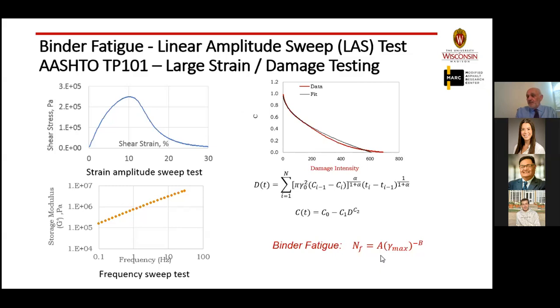So the number of cycles to failure in the binder is equal to A times strain to a power law function, or a power law constant, if you will. These A and B are related to the maximum strain. So if you look at the conventional fatigue equation, it definitely tells you it's all about the strain. If we all know this equation, and we use it in so many different applications, how come when we come to testing the binder, we only test at small strain and say, oh, well, we will figure out how to estimate the behavior at larger strains? We don't have to do that.